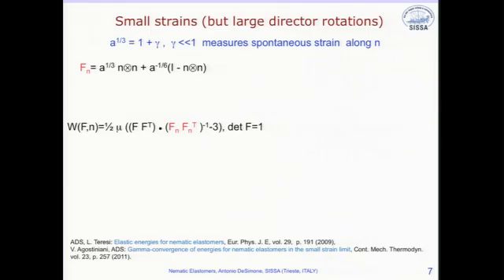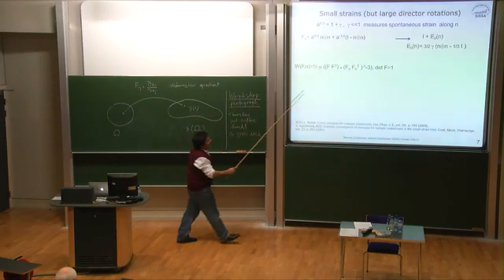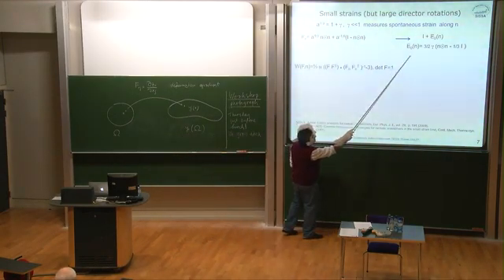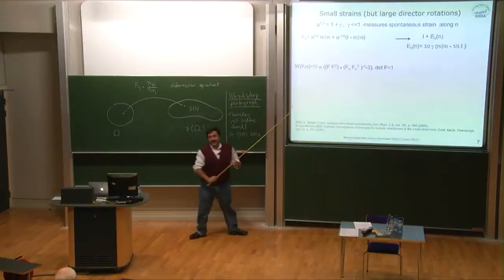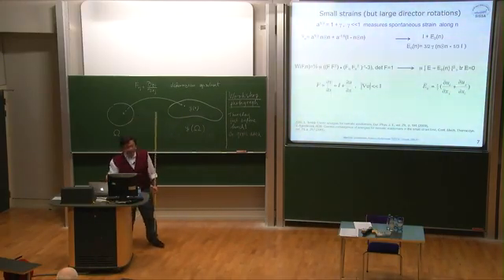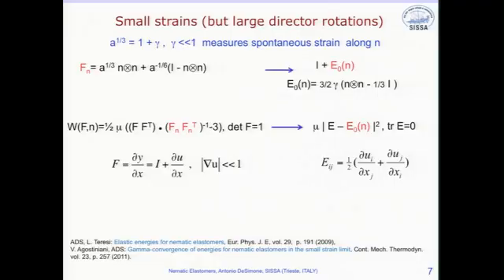And so the spontaneous strain. So from now on, I will no longer talk about spontaneous stretch, but spontaneous strain. We can calculate this by expanding this quantity, and what happens is that it's a perturbation of the identity by a tensor, which is a tensor of spontaneous strain. So you will see that something appears here, which is like the Q tensor, the de Gennes order tensor, and this is the spontaneous strain. And now we Taylor expand this energy, and what we get is a beautiful expression, because it's very easy to read.